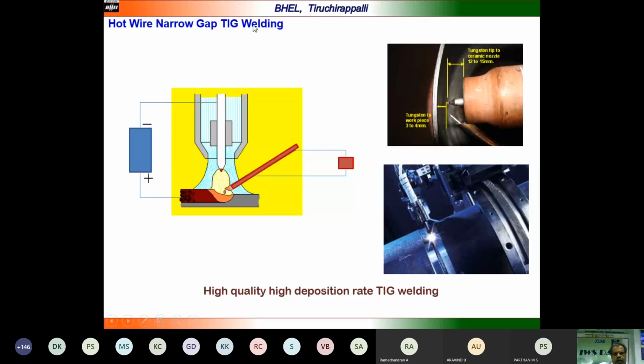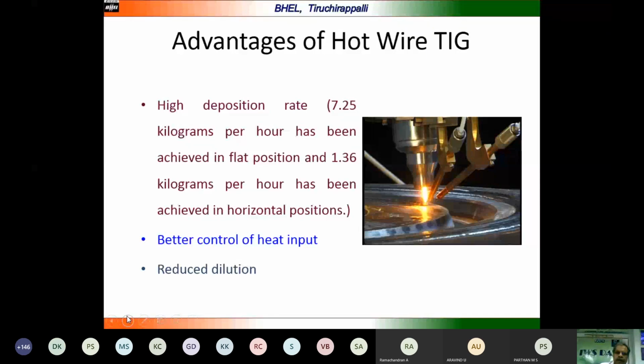This process is now used for welding even thick plates or thick shells by using this hot wire narrow gap TIG welding process. Deposition rate is almost 7.25 kg per hour, and it may be more now. In the flat position, and 1.36 kg per hour has been achieved in the horizontal position. Better control of heat input and reduced dilution are the advantages of this hot wire narrow gap TIG welding process. Hot wire TIG welding gives high quality, no spatter, small heat affected zone, and is used for narrow gap welding. Manual, mechanized, and automated motions can be used with this process.